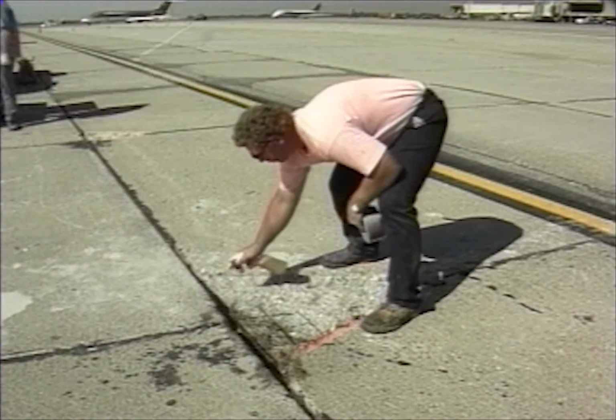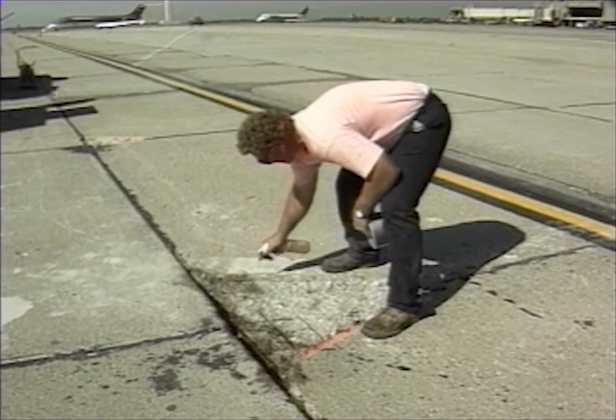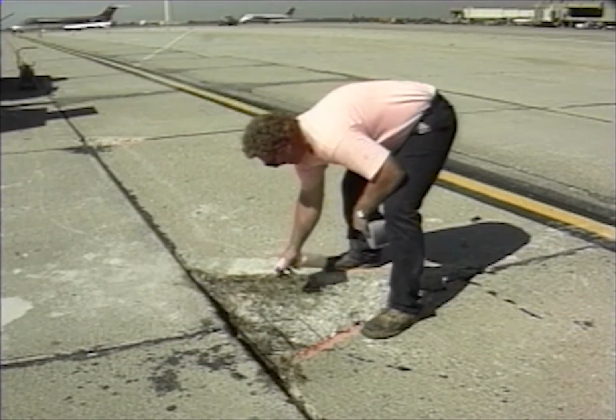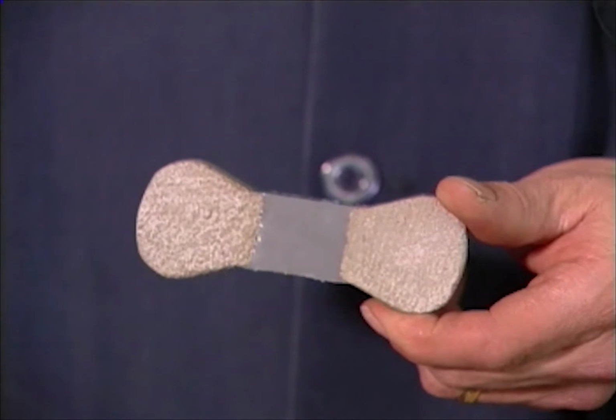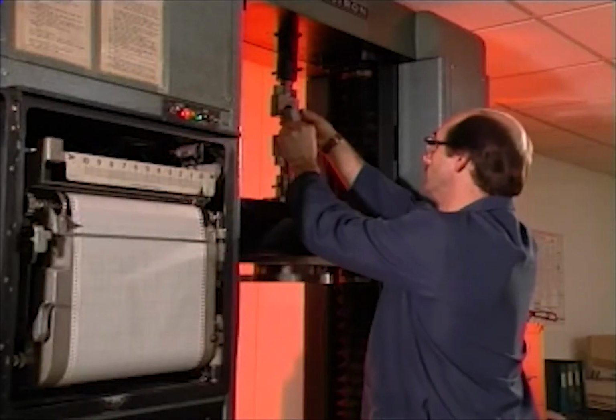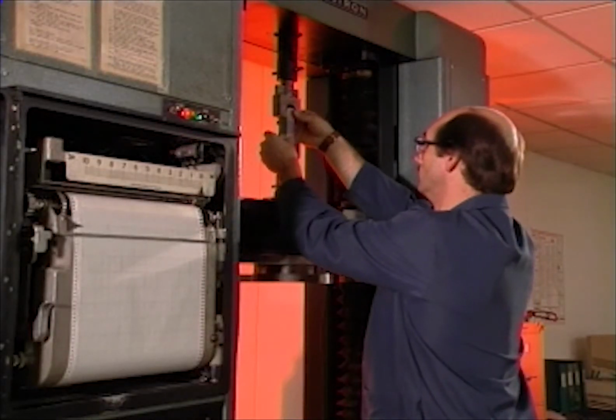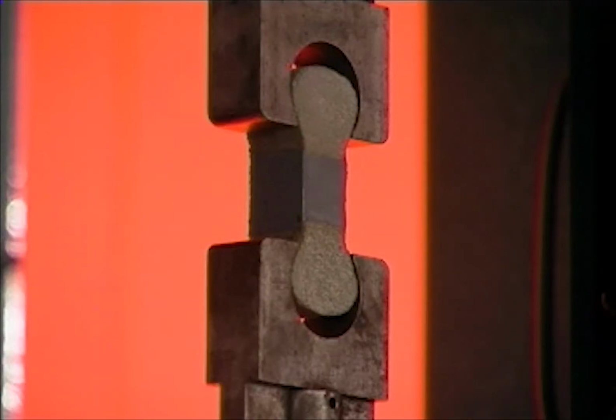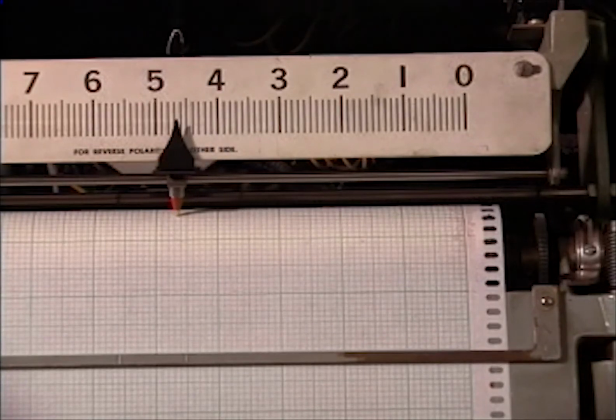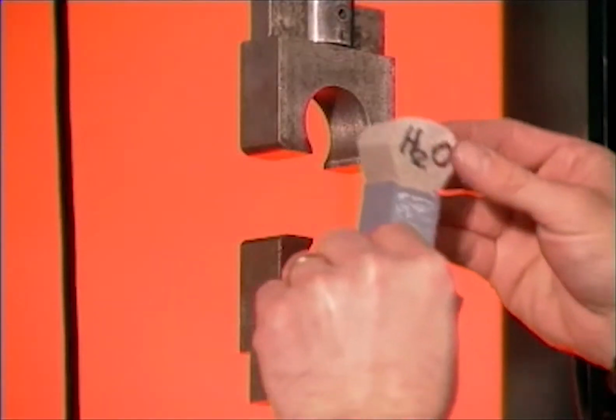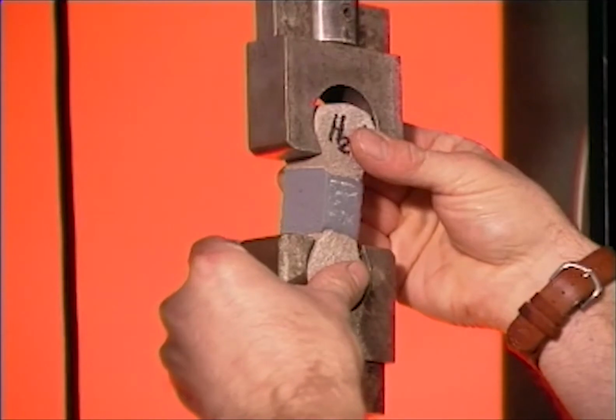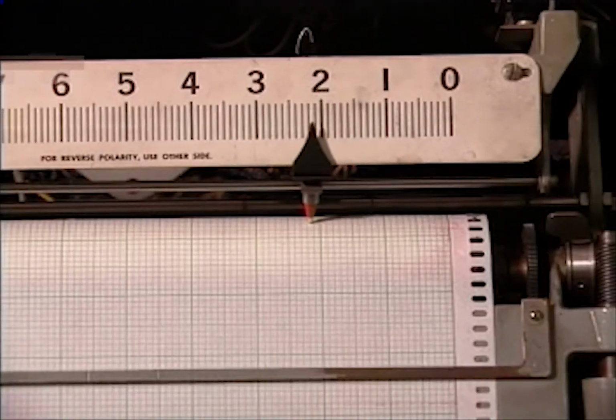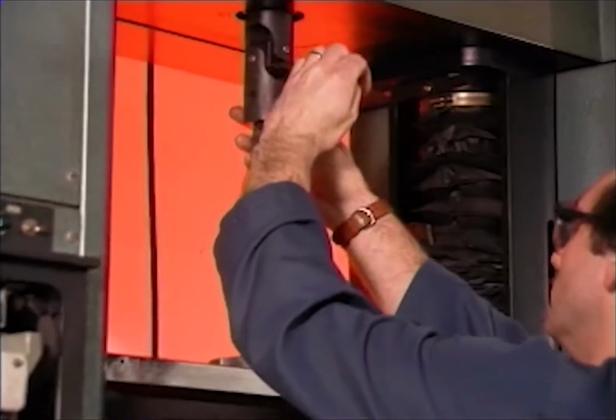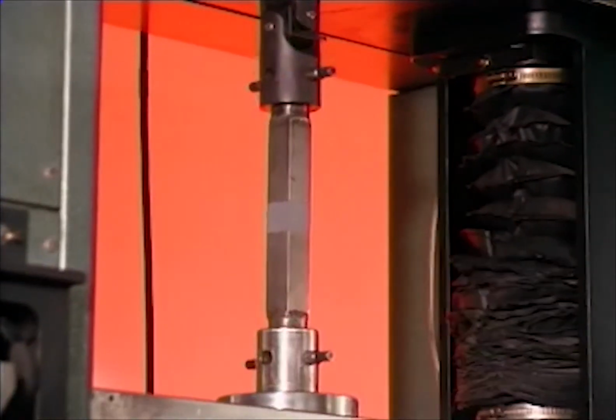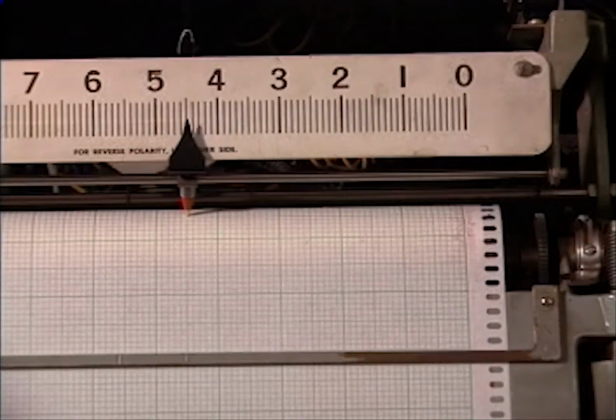Adhesion of Delpatch to concrete and steel is critical to the overall performance of any repair material. In the laboratory, adhesion test assemblies were prepared using concrete specimens with 1 square inch surface area. Using proprietary primers, adhesion values to concrete exceed 450 psi. After a specified immersion time in water, values exceeding 300 psi are routinely obtained. Adhesion to prime steel is outstanding, consistently exceeding 500 psi.